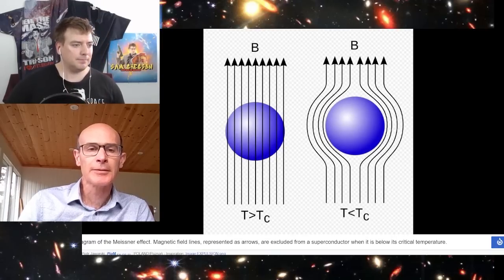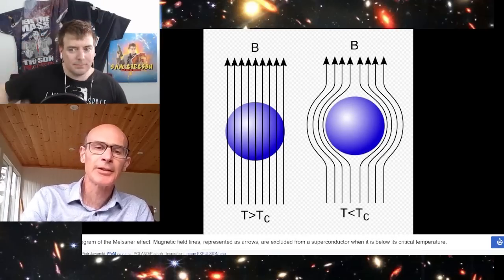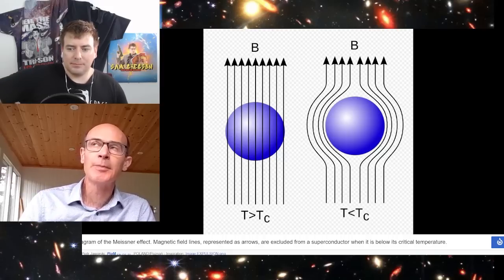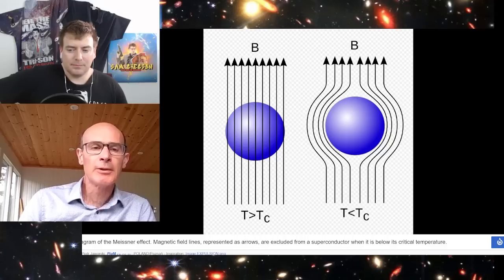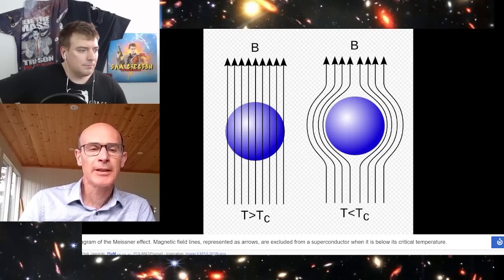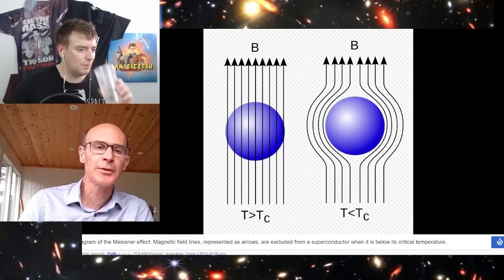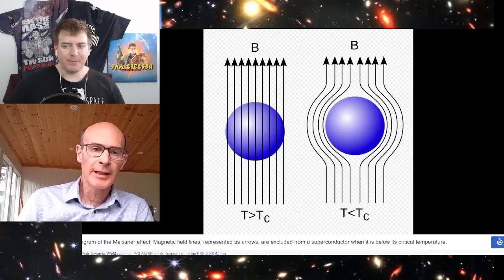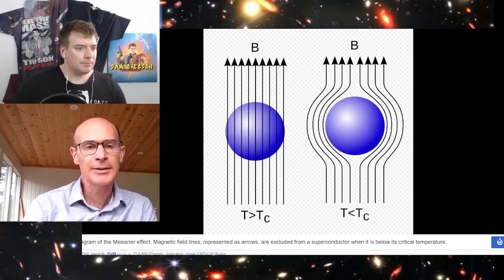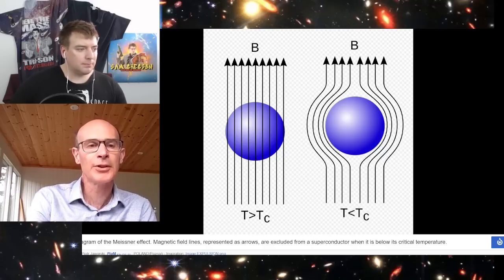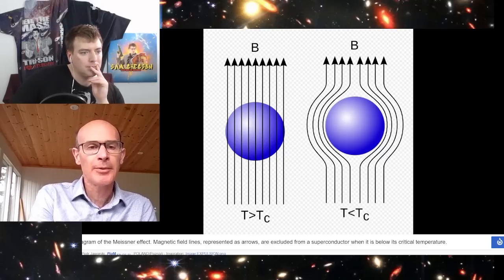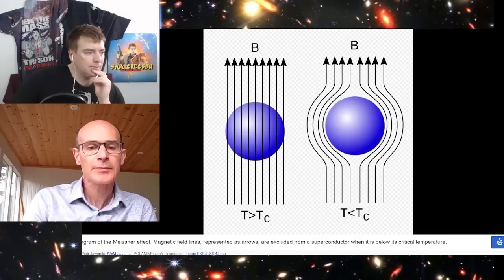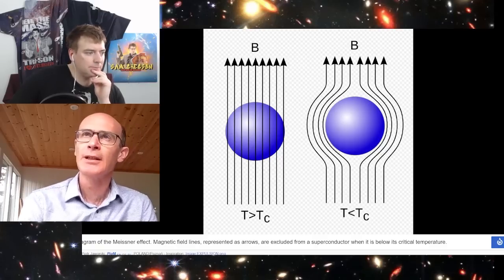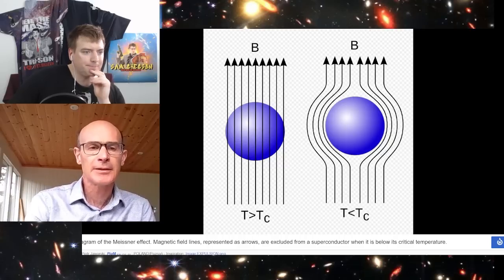So that's right. So the flux penetration above the transition, expulsion below. But in most superconductors, when you cool in the field, there will be partial penetration of magnetic flux into the sample that is preserved. So you get some trapped magnetic flux, and the sample is not quite as diamagnetic as when you turn the field on at the lowest temperature, when it was in the fully superconducting state. So that's the test, the difference between that behavior where you cool in zero field and then you cool in a field. You have slightly different responses.